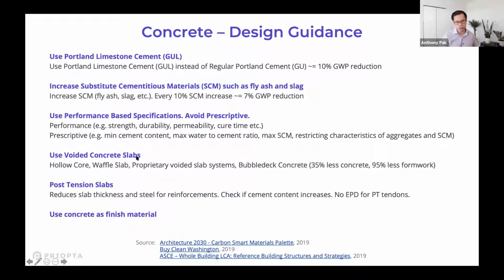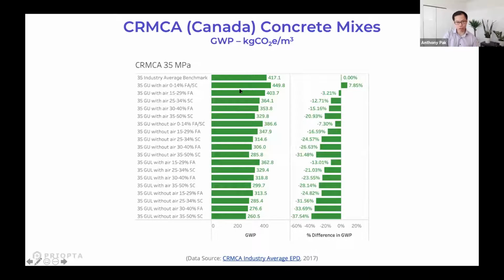I won't get into some of these other factors, but those are key strategies for concrete. Just to give you a sense of how much reduction you can achieve for concrete, this is a Canadian example. We're looking at the Canadian Ready Mix Concrete Association's industry average EPD. If you look at just 35 MPa concrete, comparing it to the benchmark mix, the average mix, if you use Portland limestone cement, that's the GUL, and you can get up to 35% or higher SCM content, you can bring it down by about 35 to 40%. I've also seen some of the manufacturer-specific EPDs lately that go much further than that as well. So a lot of reductions can take place on a per cubic meter of concrete level. So really focus on the concrete mixes.